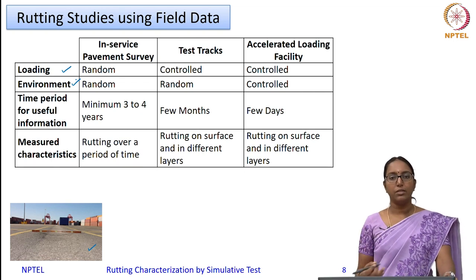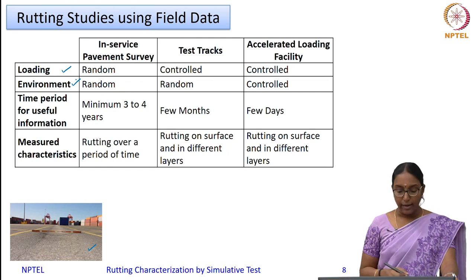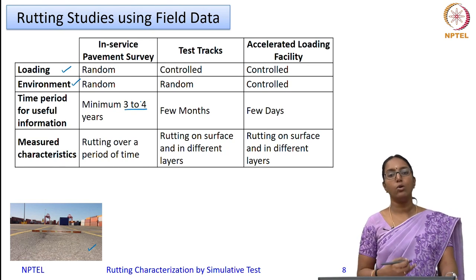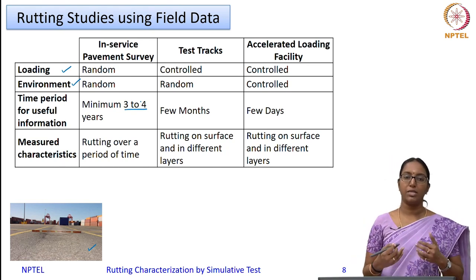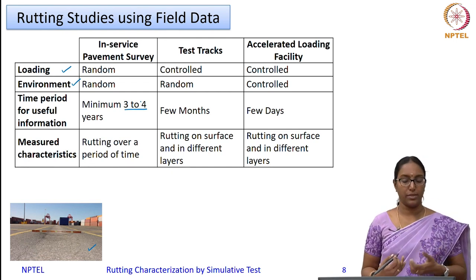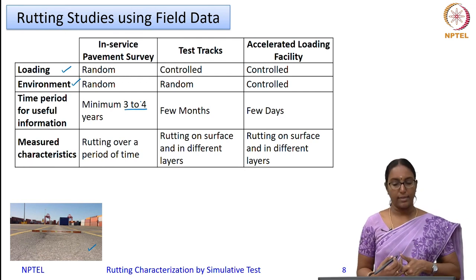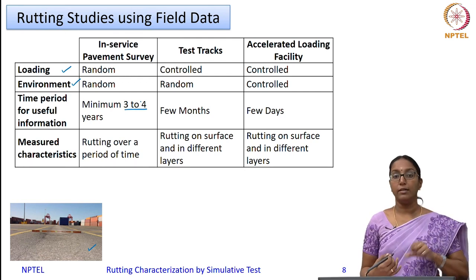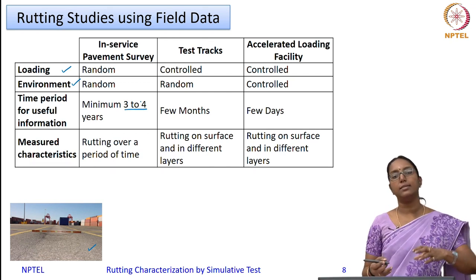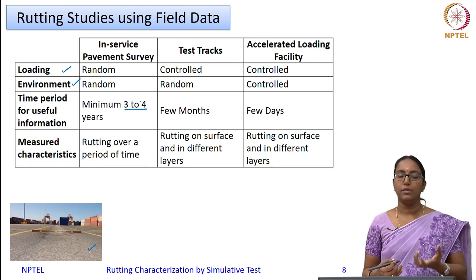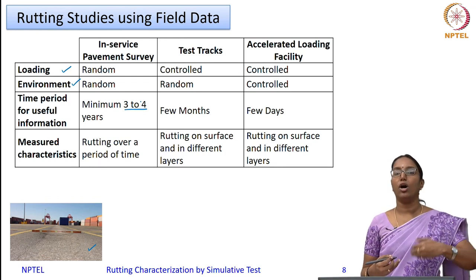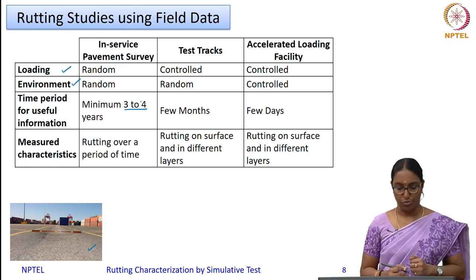The environment is random in nature as it is exposed to the atmosphere, and the time required will be 3 to 4 years. What you can measure is the progression of rutting over a period of time at different locations. Another important aspect is that you can take cores from the field — from within the wheel path as well as adjacent to it — and see how the air void content is changing, correlating it to rutting due to densification or shear flow.